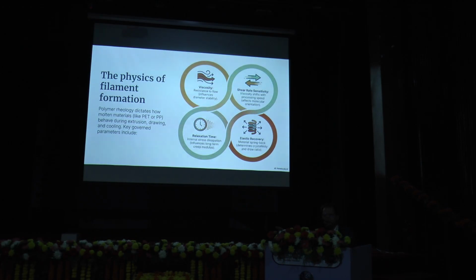Now the physics of filament formation. Polymer rheology dictates how molten materials like PET and PP behave during extrusion, drawing, and cooling. The key governed parameters include viscosity, which is the resistance to flow. This influences the diameter, so diameter variability can occur at the filament stage. That is what we are stipulating. Shear rate sensitivity, how the various layers react with one another, relates to the processing speed. This is likely to affect the molecular orientation.